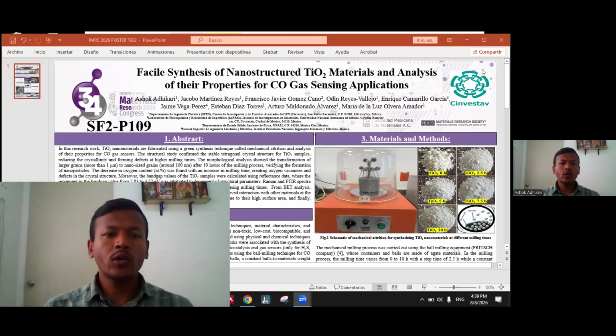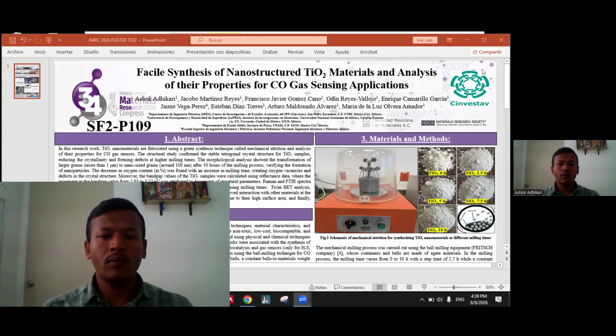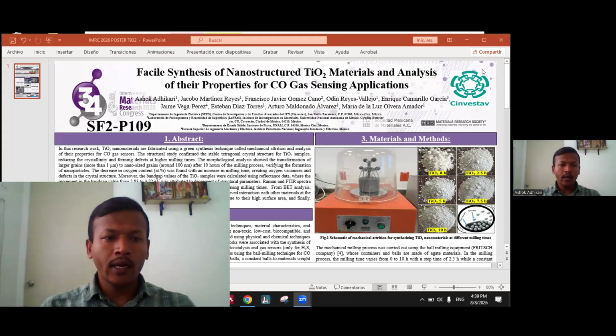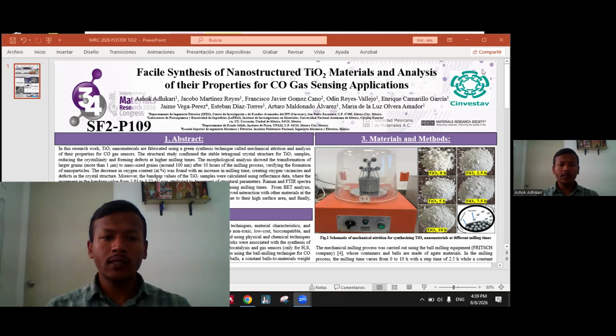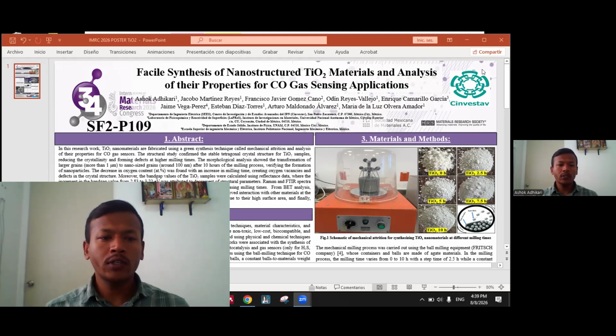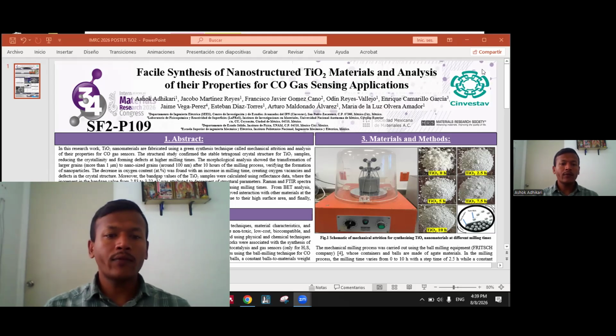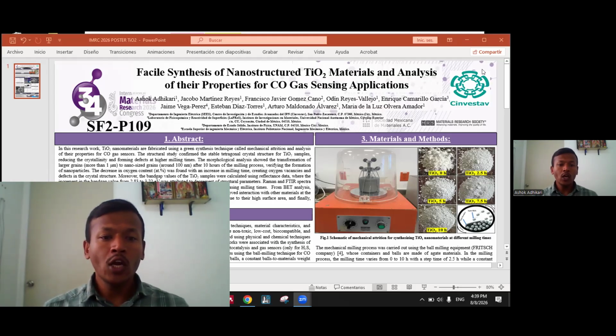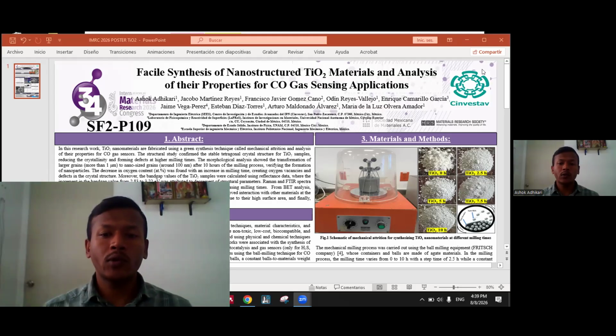So in this research work, TiO2 nanomaterials are fabricated using a green synthesis technique called mechanical milling, or simply we can call it the ball milling technique, and analysis of their property for CO gas sensors. The structural study confirmed the stable tetragonal crystal structure for TiO2 samples, reducing the crystallinity and forming defects at higher milling times. The morphological analysis showed the transformation from larger grains, more than 1 micrometer, to nano-sized grains around 100 nanometer after 10 hours of milling process.